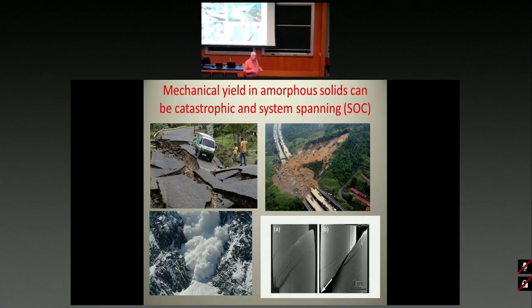A single one always has a very strong tendency to crystallize. If you cool down copper, it will crystallize, no matter at what rate. But it was already understood 50 years ago that if you take a binary mixture of metals, say copper zirconium, and you cool it very quickly, okay? In those days, what they did, they took a melt and they splashed it on a cold substrate. It will go through a glass transition and will not crystallize.